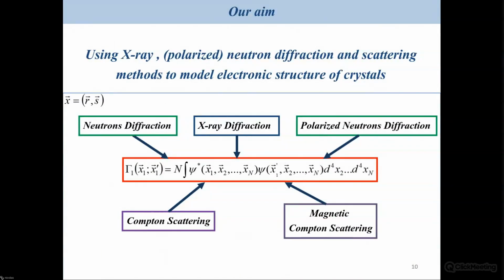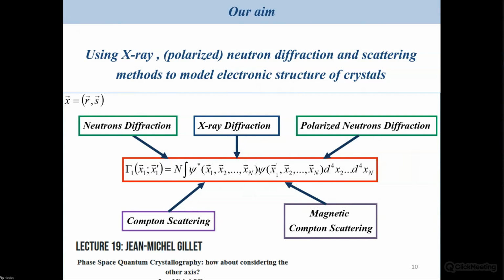Our idea, in a very huge project, was to combine many different experiments in the same model. Of course, we talk about neutron diffraction and X-ray diffraction, but also polarized neutron diffraction. In our idea, we also imagine it could be possible to combine Compton scattering and magnetic Compton scattering to have a very complete overview of the system. For that, the tool that can be applied for introducing all the elements together was the one-electron reduced density matrix. I will not describe that matrix too much, because Jean-Michel gave a very detailed lecture previously on that subject, and I recommend looking at that presentation again. What I'm focusing on is the way you conduct that joint refinement.